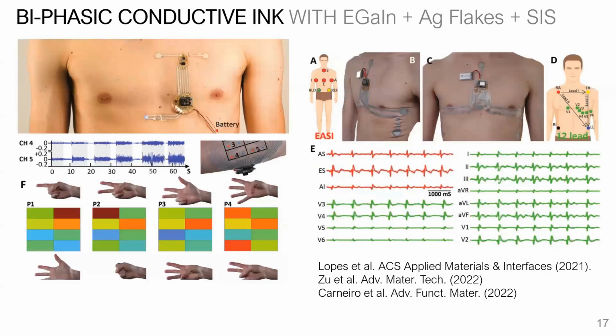And so I'll just briefly, and we've actually done extensive study on looking at these materials as bioelectronic interfaces. So EMG, EEG, ECG, interfacing with electronics, surface mounted components to make these fully wireless and compatible with Bluetooth. So these are all things that we've explored, and I'll save you all the details. But in terms of the skin, the impedance matching with skin and the ability to achieve high signal to noise ratios, these actually perform on par, or in some cases outperform silver chloride gels and other gold standards for bioelectronic interfaces. So here you have both a high electrical conductivity, but you also have this soft rubber compliance that allows for really good interfacing with the body.